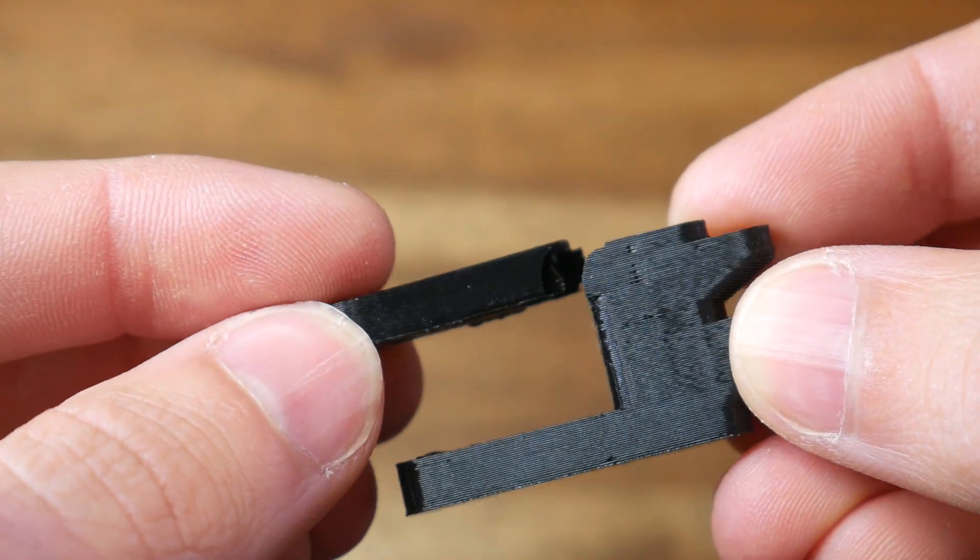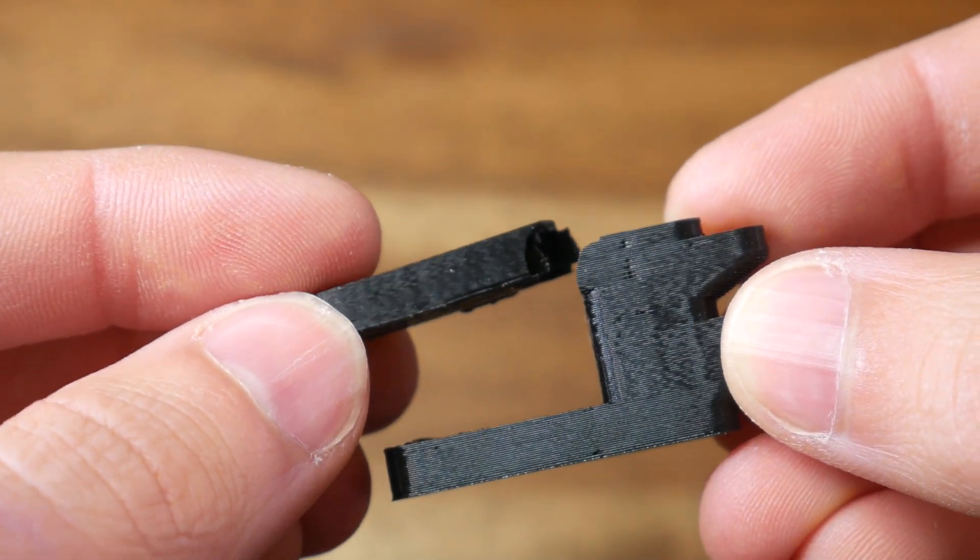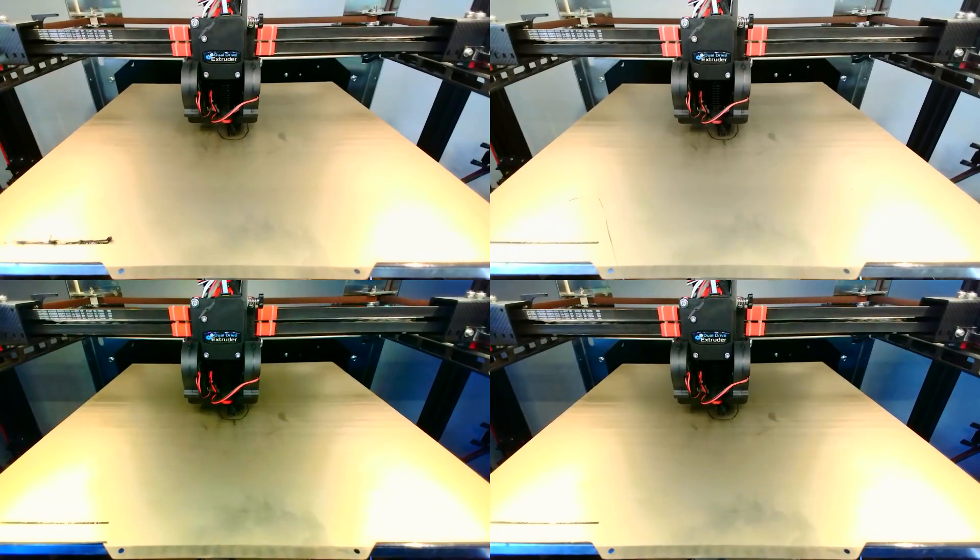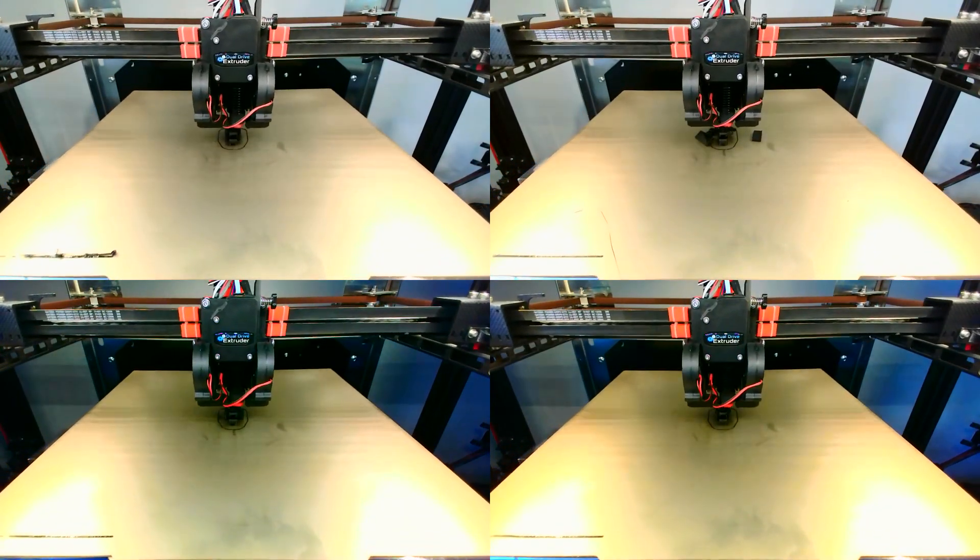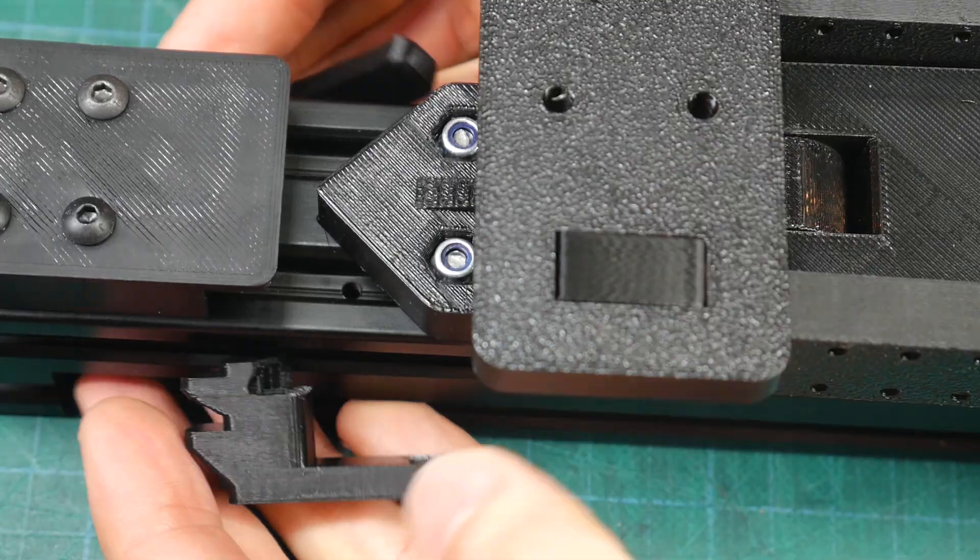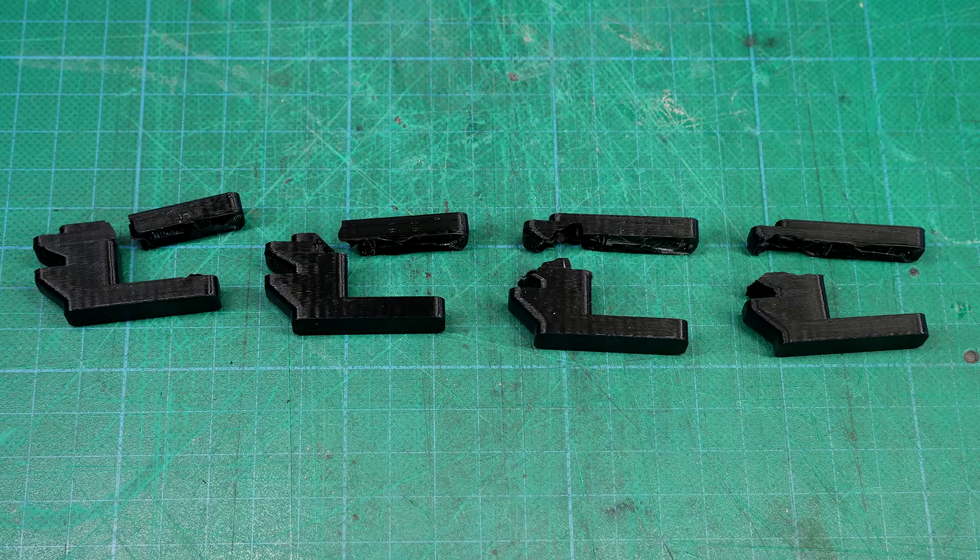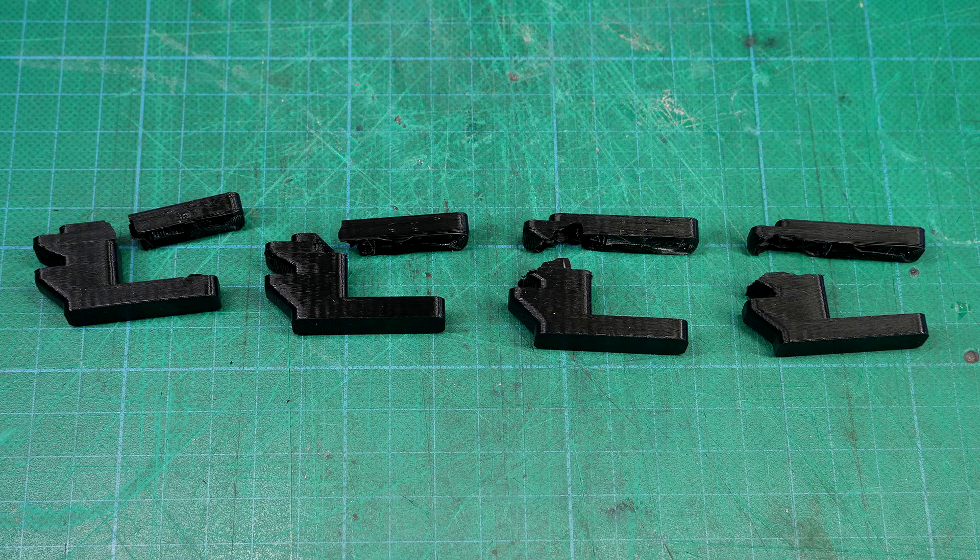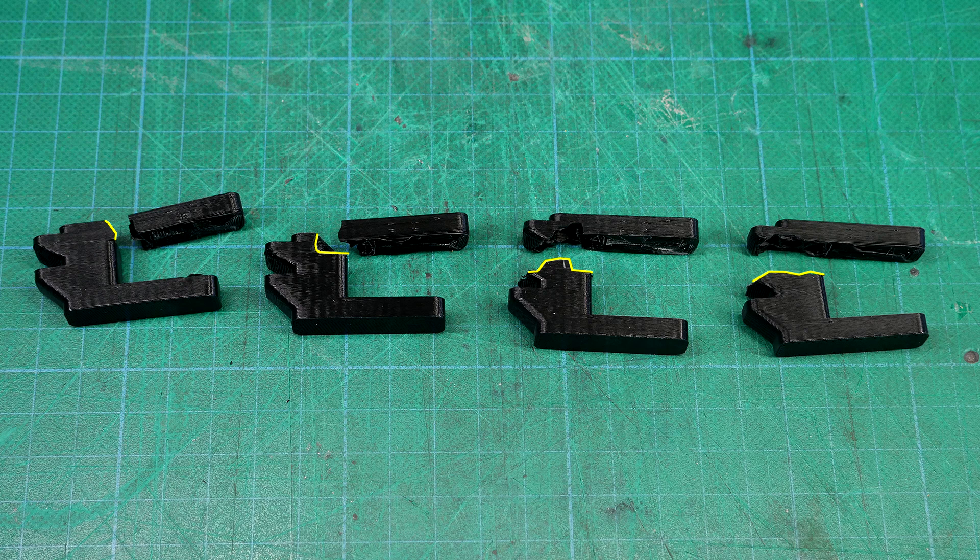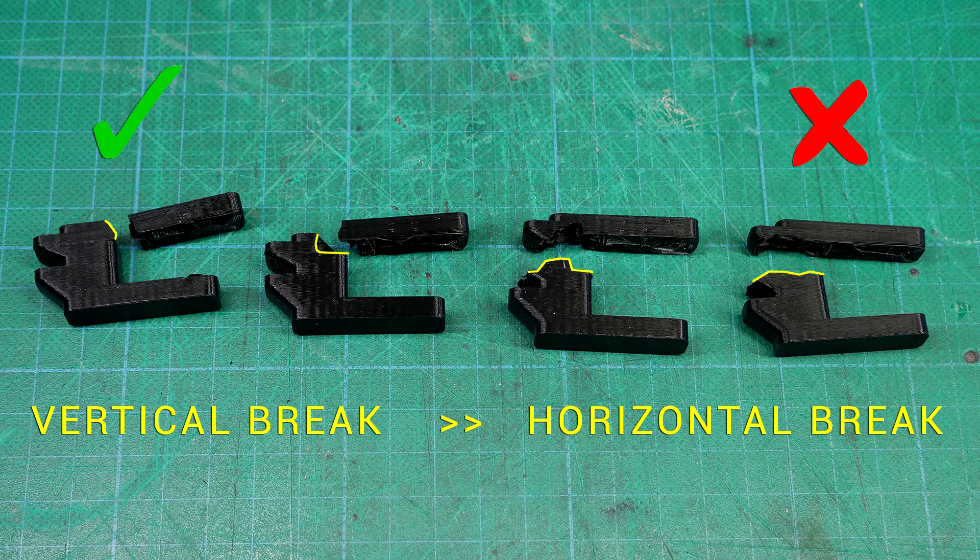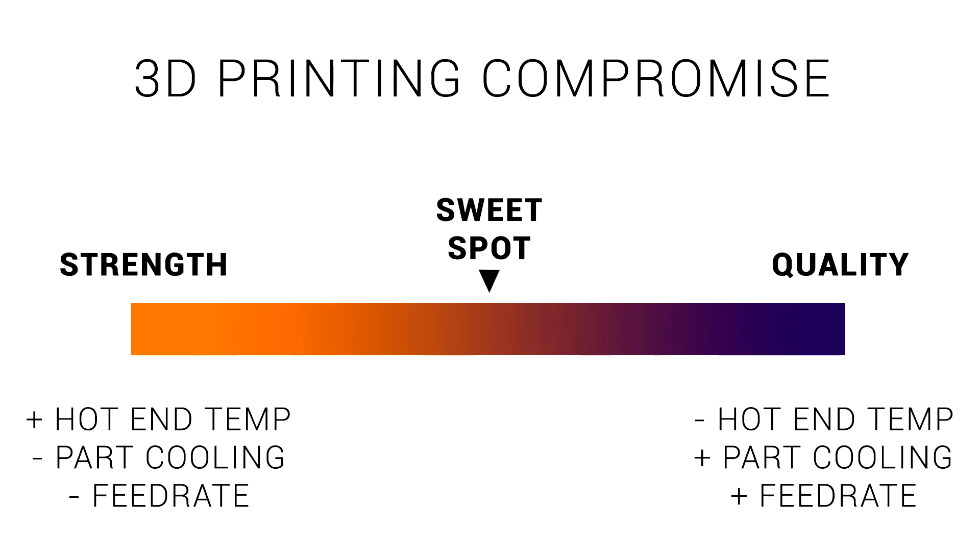But how much can I drop the temperature before things start to look bad? I ran some back to back tests to judge just that. And I'm pleased to say the results were encouraging. Each of these tests, from left to right, drops the hot end temperature by 5 degrees Celsius. And if I highlight the surface in which the model broke, you can see that it transitions from a vertical break, through to a horizontal split where the layers aren't welded properly. What I'm pleased about, is that by changing a single one of these variables, that practice was able to match theory. With the power test piece and the Kraken being a suitable way to show this.